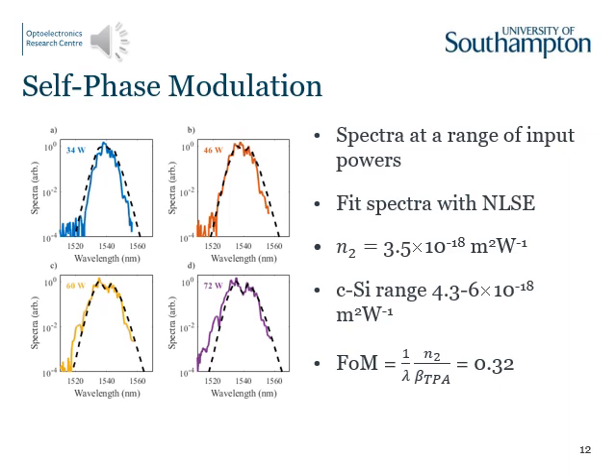The nonlinear figure of merit from our beta TPA and N2 is 0.32, at the lower end of the typical range from comparable waveguides. However, the low nonlinear quality is contrasted by the low optical losses, which provide a low power threshold for the operation of devices in this material.